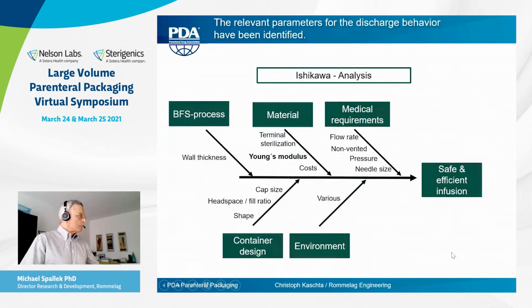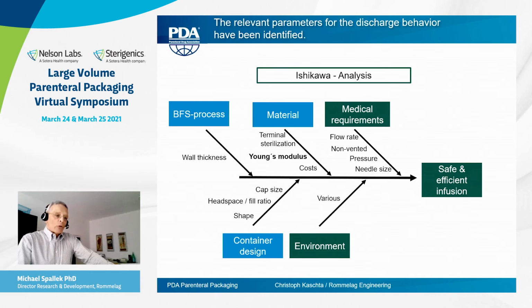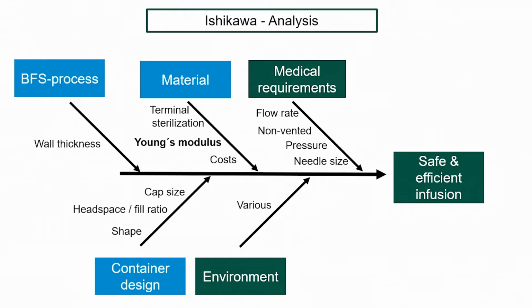How did we approach that? Thinking first into the categories of an Ishikawa analysis gives you the main parameters you can play with. In our case, our target is having a safe, efficient infusion administration and having a non-vented system. We can play with material, BFS process, and container design. We cannot influence the medical requirements dramatically. So material-wise, the most important parameter certainly is the Young's modulus. For the BFS process, the wall thickness and the wall thickness distribution is important. Whereas for container design, the shape and the headspace to fill ratio is important. So playing around with these parameters was the goal to get into a good solution.